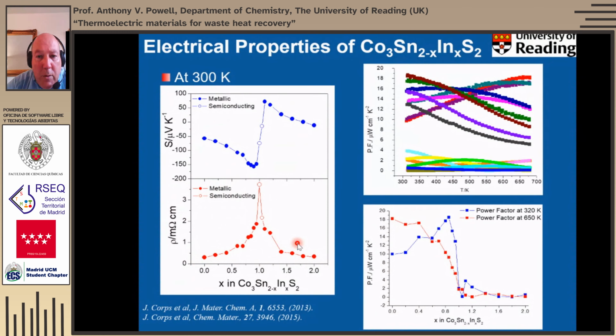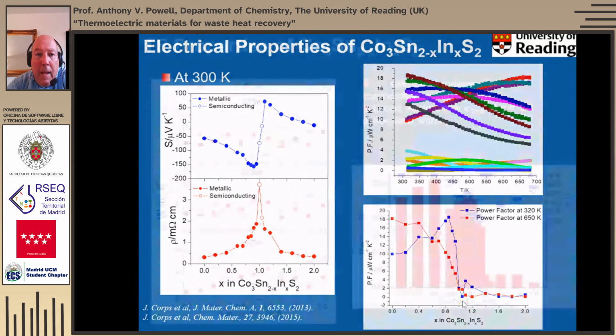as a result of chemical compositional changes. When we get to that second metallic region, the Seebeck coefficient never really recovers. It doesn't get the values that we get before that halfway point. And as a result, the power factors beyond that 50-50 composition tend to be quite miserable compared to those before that 50-50. And we can see that graphically here at 2 temperatures. It sort of falls off a cliff edge as we get to that 50-50 composition.